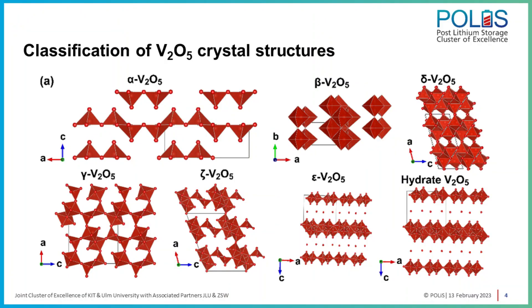First of all, thinking about vanadium — vanadium is abundant. It is the 20th most abundant element in the Earth's crust. Another advantage is that vanadium has four different oxidation states, making it very versatile. There is also quite high capacity with respect to other cathode materials. These are the attractive properties for this material to be used as a cathode.